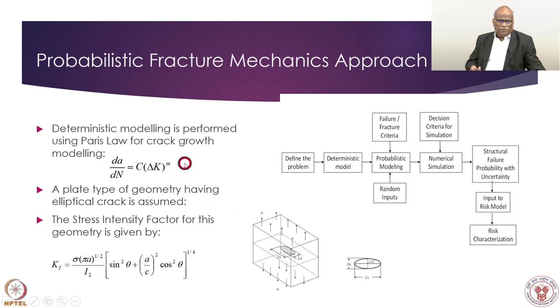So here for demonstration purposes, a thick plate geometry has been considered, and the crack initiation component we have not modeled. We have assumed that a crack having aspect ratio of 2a and 2c is there in the subsurface of the material, and then we have the stress intensity for this particular geometry. Given the location of the crack, the stress intensity is given by this model, where the ratio of a to c plays the role of a function of intensity along with the sigma value.